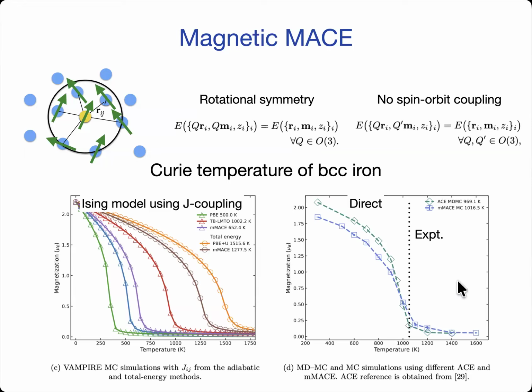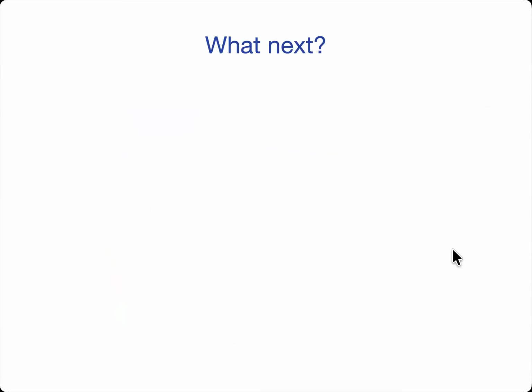And when you do a direct simulation, so this is basically taking the MACE model fitted to iron DFT data with explicit spins, that's the blue line, with this magnetic MACE model, you basically get the Curie temperature that you should be getting, which is about 1,000 K. That's one of the literature values also. When you do this with ACE, then you also get the same answer.